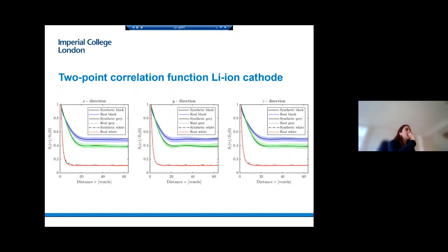Now we also perform a calculation of what is called a two-point correlation function. So basically what the two-point correlation function does is that if you have 2 pixels, it calculates the probability that both pixels belong to the same phase as a function of the distance that separates them. So basically at the beginning they're correlated, and as the distance becomes larger, you can see that there's no correlation between one voxel and the other. So this is a very important metric that is used for analyzing long-range properties of porous materials.